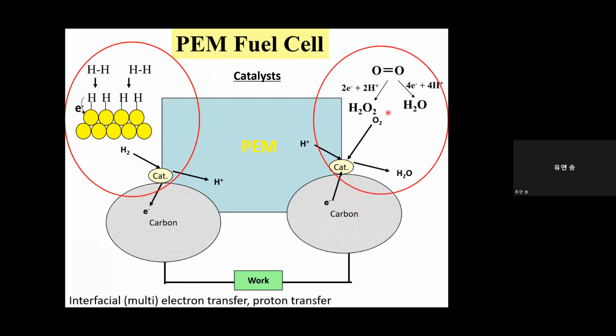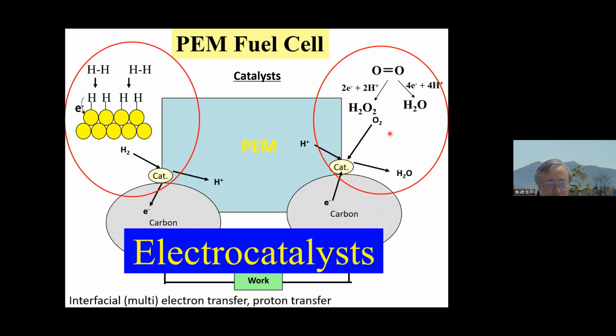On the other side, we must reduce oxygen. Oxygen reduction can go to hydrogen peroxide or water. Of course, we want to reduce oxygen to water. In that case, we must break this O=O double bond, which is more difficult than making hydrogen peroxide. In the case of hydrogen peroxide, you just add 2 protons to both sides. But in this case, you must have more complicated 4 electron, 4 proton steps. So we need a very good catalyst. So we call it electrocatalyst.